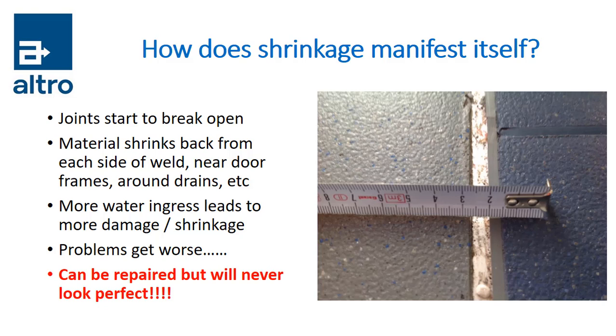The picture on the right, by the way, was a job that was seen not so long ago, and you can see how much it has shrunk. If you look down the weld, you can see that the right hand side was still attached, but the left hand side has come completely off, mainly because it wasn't welded properly. It was also the wrong type of adhesive, and it's been washed away.